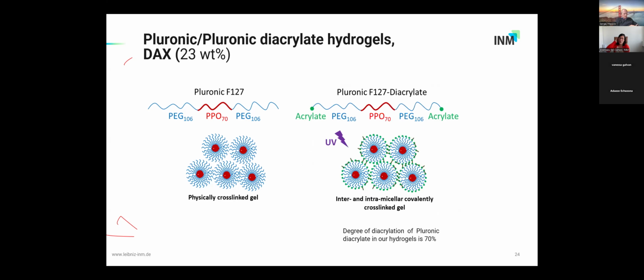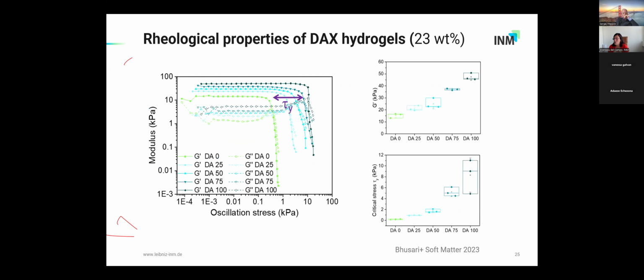You can also mix pluronic with pluronic diacrylate and then form a physical hydrogel in which you can impose a chemical cross-linking as well without disturbing the physical order. That allows you to make hydrogels in which you can control the physical properties. You don't change the solid content, you only change the amount of chemical cross-link on top of the physical cross-link. And you can generate gels, which you can also mix with bacteria, you will see in a second, with shear modulus between 10 and 50 kilopascals, and also polymers which have a critical yield stress between a very low one and 10 kilopascals. So this is important also in terms of deformation, or the possibility of the biofactories to deform them.